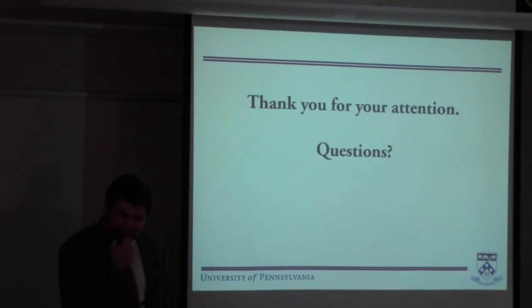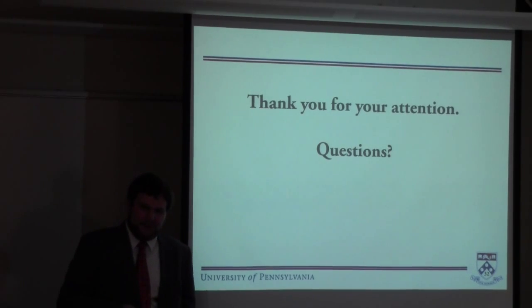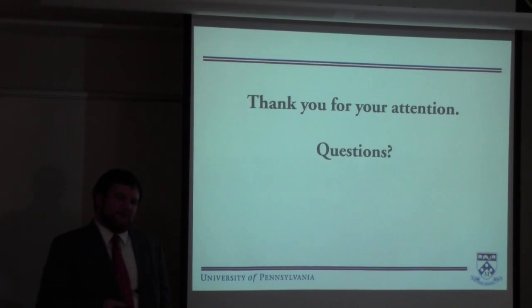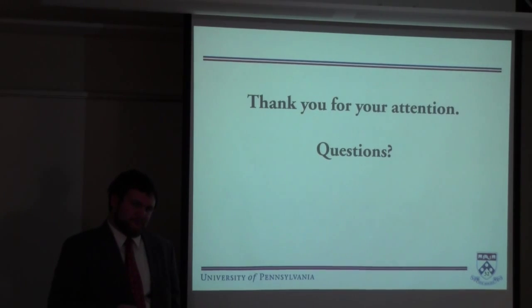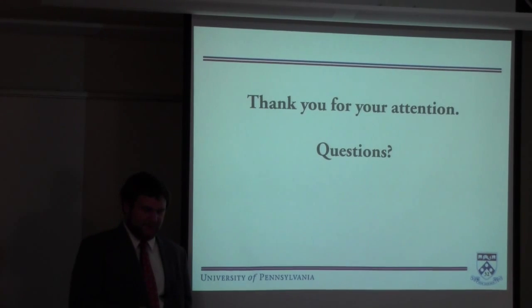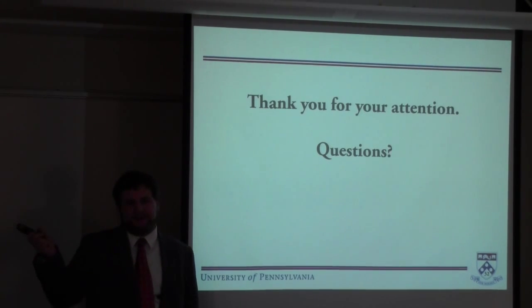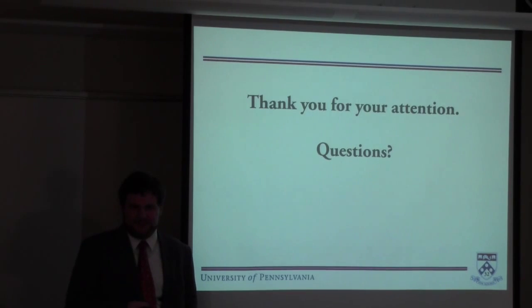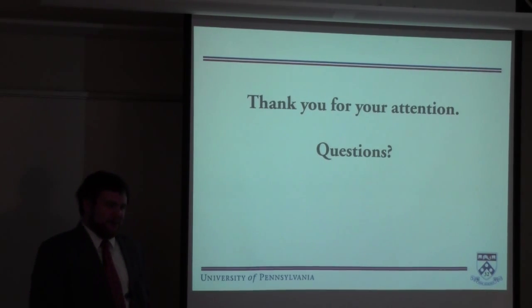I do have a question on the minimal feature size you have currently, and if you push further down, what would the obstacle be? So, the minimum feature size on these was 5 microns, and that's limited by the contact photolithography we're using right now. Anything smaller than that, we've had resolution issues, such as blurred contacts. So the smallest feature size we've been able to make so far was 5 microns.